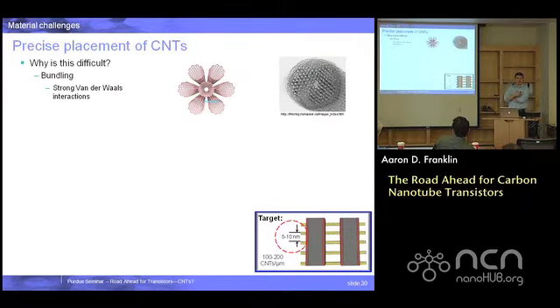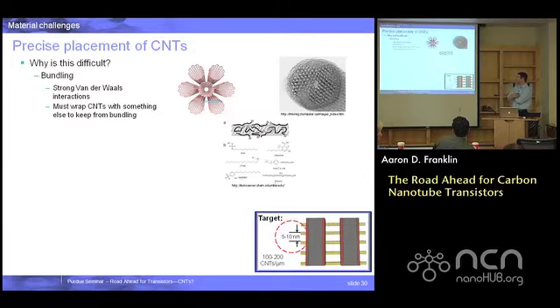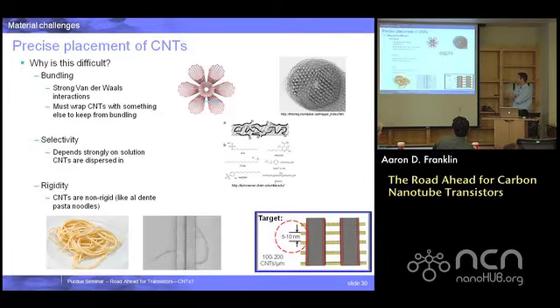Nanotubes are not rigid structures, at least not in most of the ways that they are placed on a substrate. And I have a comparison down here. I like to think of them as sort of al dente pasta noodles. If you just spin them out on a substrate from a solution, they're most likely going to look something like this guy, wrapped around there, instead of nice and rigid like something that is not hollow, like a nanowire would be. So this is something that has to be dealt with not only from controlling the orientation of the material, but also keeping it from interacting with its neighbors.